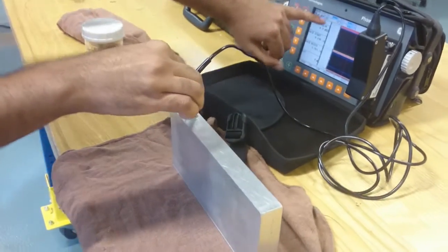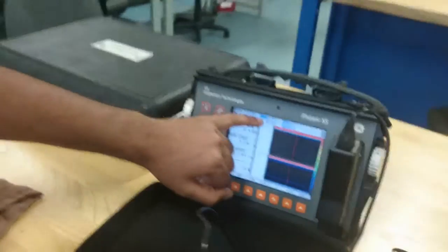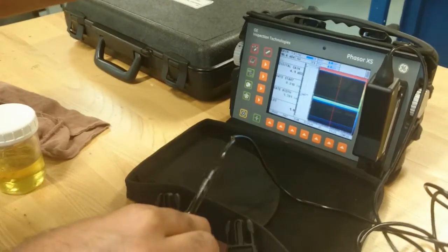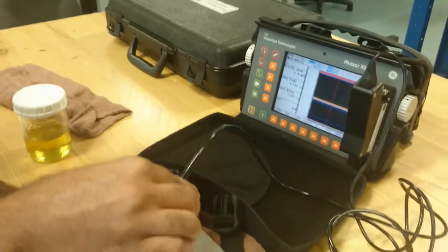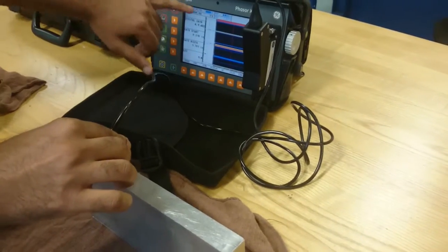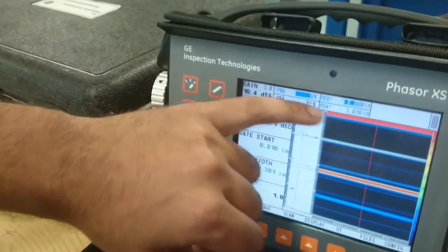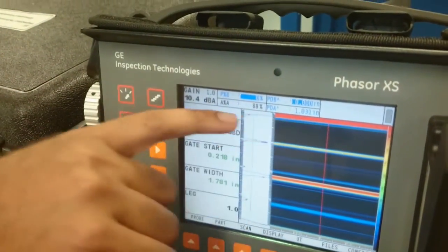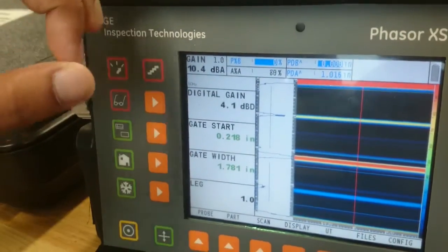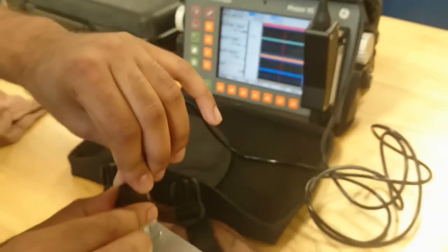we look at this percentage here. It's 6 to 7%. When this percentage reaches around 50 to 100, it means we have found a hole. Look at this. So we found a hole at this depth. This is the depth and this is the percentage, so it's over 50%, so it's surely a hole or an irregularity over here. So we just place it,